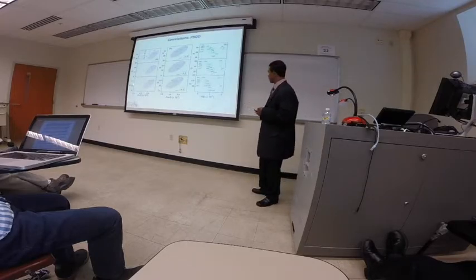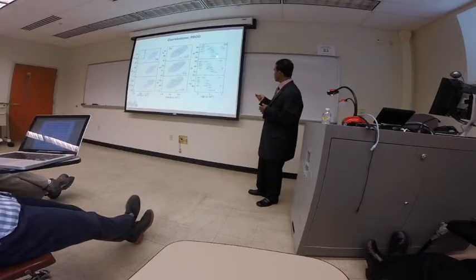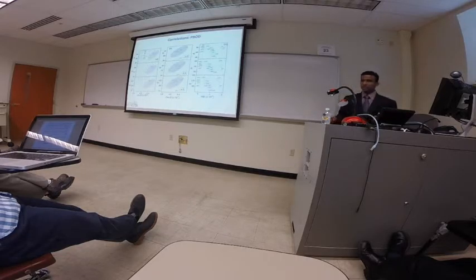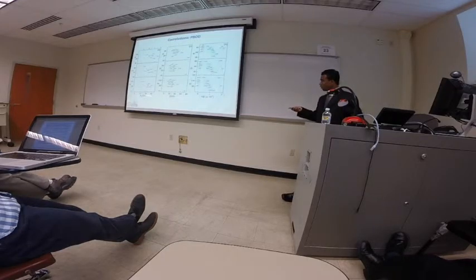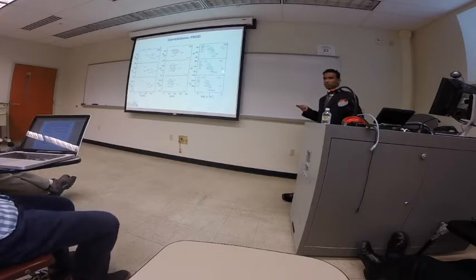Calcium oxide, on the other hand, shows much better correlation, well, relatively speaking. But interestingly, hydrogen bond order density gives at least relatively the best correlation. When you increase the hydrogen bond order density, the mechanical properties go down, but surprisingly, at some instances, they go up again. The only deciding factor is hydrogen bond. So that was not known before. So to test the idea, is it just because of hydrogen bond order density? Is it just electronic structure or just the number of water molecules? We plotted percentage water and percentage hydroxyl in these crystals, and we found out they don't make much correlation. So it is indeed the strength of the bonds and the number of bonds that decide and correlate with the mechanical properties.